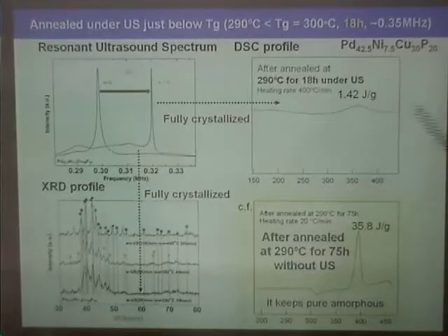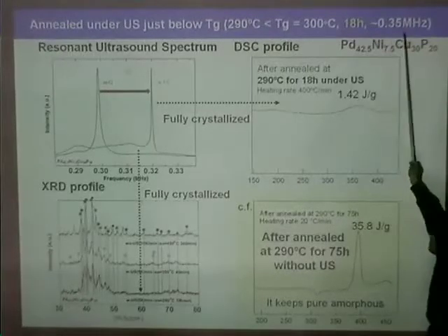But when the sample was annealed without the ultrasonic vibration, it kept pure amorphous alloys. For example, after annealing at 290 degrees centigrade for 75 hours, very much longer, but without ultrasonic vibration, it keeps pure amorphous alloys. So the structure is very sensitive to the ultrasonic vibrations.